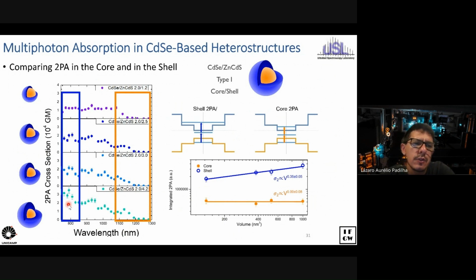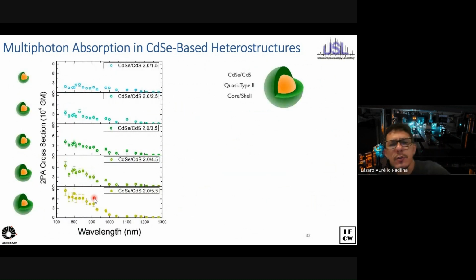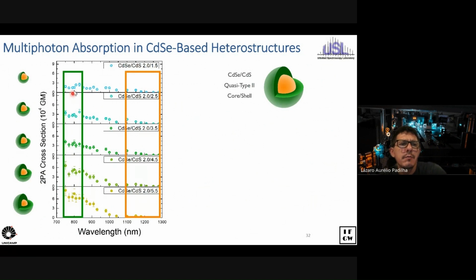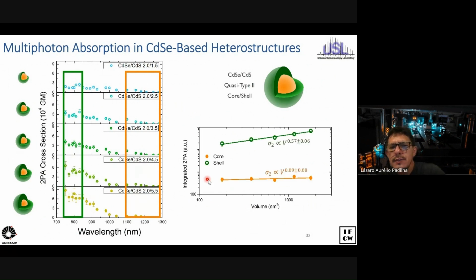So indicating that, of course, only here the shell influences. The same is true for the quasi-type 2. If you take this green region and the orange region, we see a slight dependence here, which is within the error basically, which could be some dependence because if you think the electron experiences the whole structure, you do change something on the interactions. So you change something on the density of states also. But you see that the dependence is, of course, much stronger above the band gap of the shell.